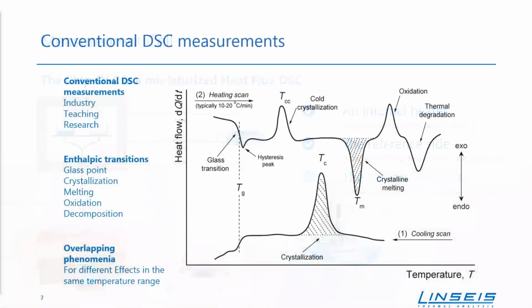Okay, so this is basically the chip DSC, but what are we looking for with this device? Here you can see a diagram from the literature. In this case, it is PET, also a reference material. And here you can see some different transitions. In the upper measurement, you can see there's a transition peak in the beginning. Then you can see the cold crystallization, crystalline melting, and oxidation or thermal degradation. Below this measurement, you can see the cooling, and the cooling is just the crystallization.